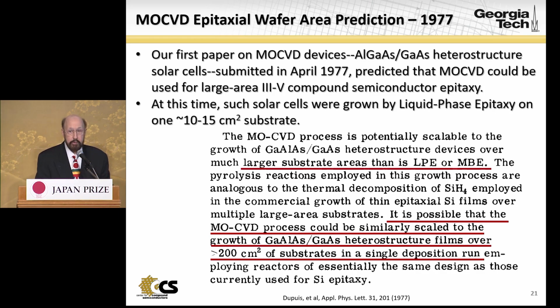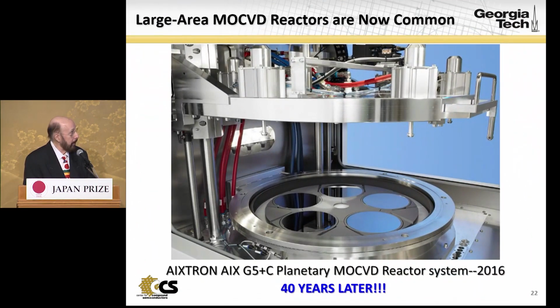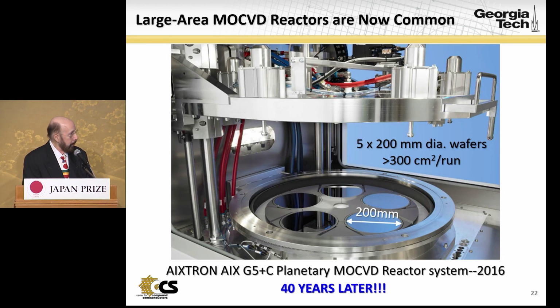This was kind of a crazy story at the time because no one had a technology to make heterostructures of any reasonable size beyond about 2 inches was the limit. Nevertheless, today you can buy very large reactors. This is an example of an Aixtron reactor developed around 2016, so 40 years after my prediction. This tool has a capacity for 5 200 millimeter diameter wafers, or greater than 300 square centimeters of substrate area per run, and there are even larger reactors available today.